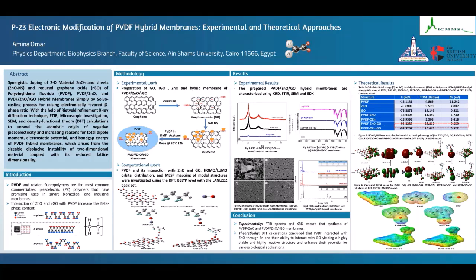The experimental work focused on preparation of graphene oxide and reduced graphene oxide, zinc oxide, and forming hybrid membranes of PVDF with zinc oxide and reduced graphene oxide. And the computational work used calculated optimization and mapping of electrostatic potential for this interaction between zinc oxide and graphene oxide.